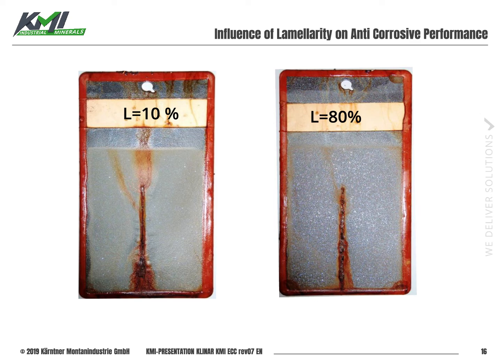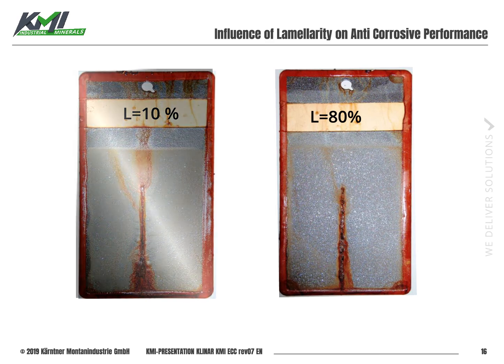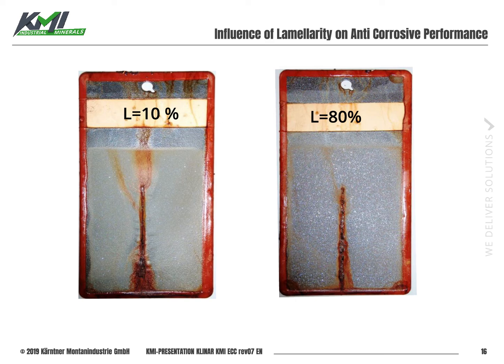Now to the test results. What you can see here are the test panels after this 25 weeks combined corrosion and weathering cycle. Here you can see the 2-layer systems, so you have a 2K zinc phosphate as a primer and the 2K epoxy on the top. The only difference between these two test panels here is the quality of MIO. On the left hand side you can see the grade with only 10% of platelets, and on the right hand side you can see the standard grade with 80% of lamellas, which is our Miox SG grade. And there is a big difference in the performance.